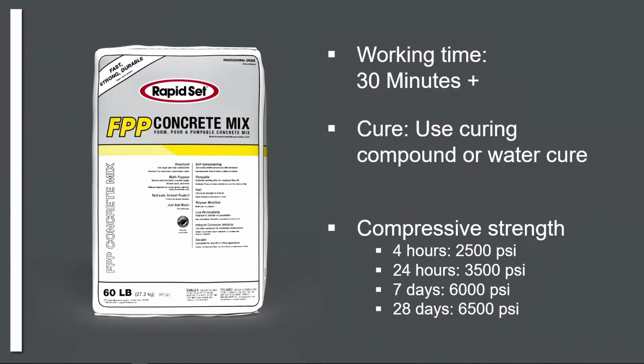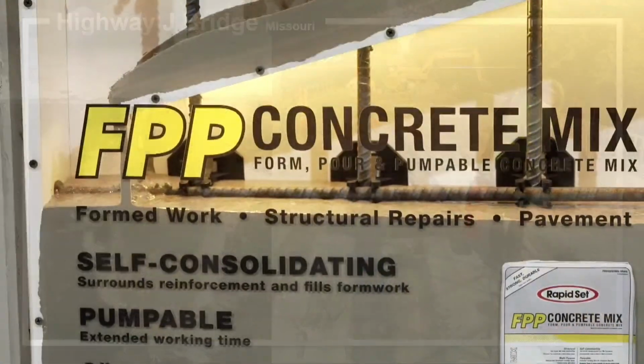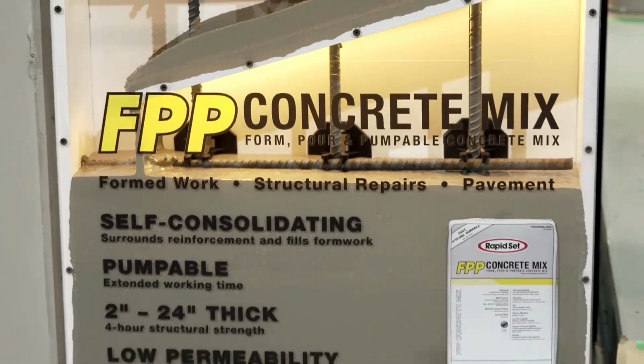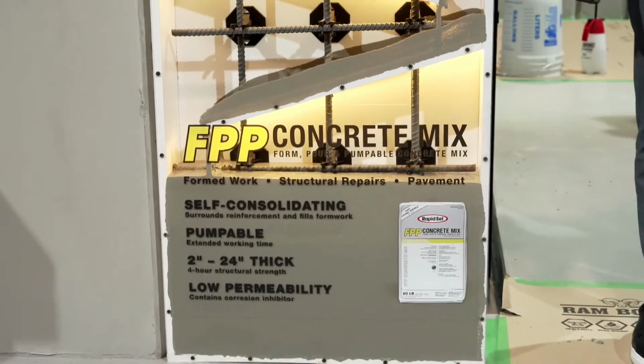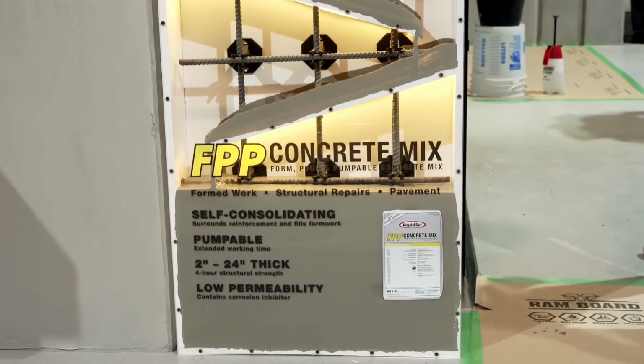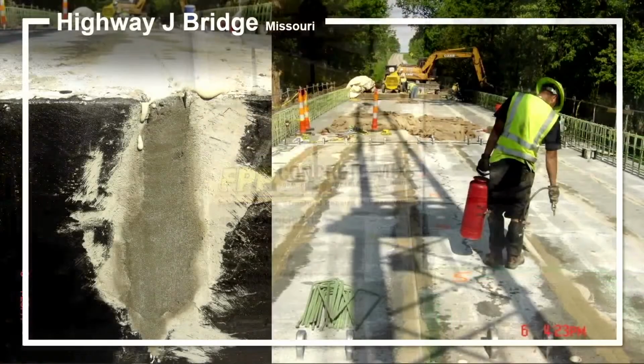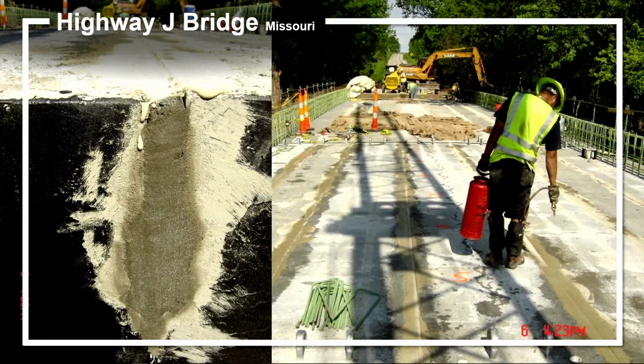The other key benefit of the FPP concrete mix is it's designed to stabilize that aggregate. So even though it's got a very high flow, it's designed to have the aggregate stable all the way through the mix. So we'll talk about a few projects. Up on the screen, you'll see the Highway J Bridge. This bridge got top marks by the National Bridge Inventory for deck, substructure, and superstructure after they used the Rapid Set Cement All to grout the keyways. The requirement on this was 3,000 PSI at 24 hours, and the Cement All achieves over 7,000.